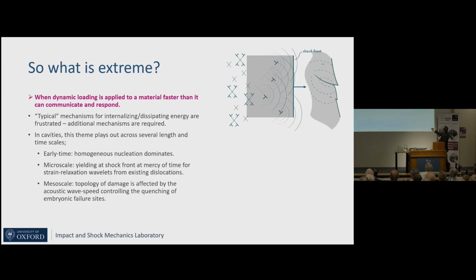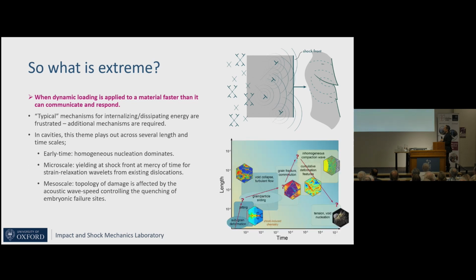So we see this play out in a variety of different length scales. In the interest of time, I won't belabor them, but effectively at the large length scale, we saw that an initial shear crack would extinguish adjacent shear cracks. We saw that when dislocations move, their effect isn't felt until some time later, and that will relax the front. And if we go to even higher strain rates, then we can drive the system to produce its own dislocations because there aren't enough dislocations in the body to accommodate that strain.